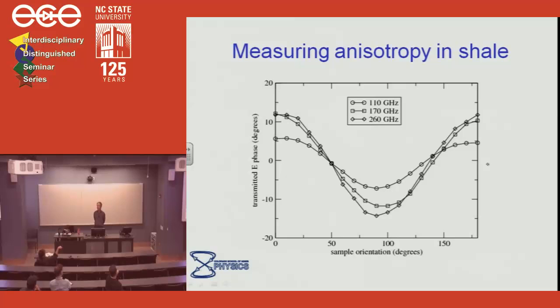You're seeing the phase of the electric field as a function of the sample orientation. So we've got a beam that's vertically polarized, and we've got a sample that's layered. So as we rotate the layering relative to the beam, you see the anisotropy. That's right. So that's the rotation of the beam, and this is the extent of the anisotropy. And it gets more anisotropic at higher frequencies because it turns out the waves start to resonate with the layers.